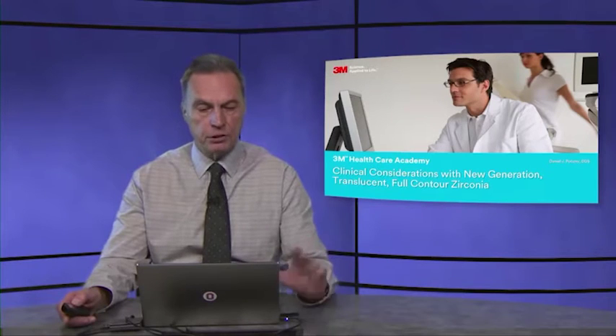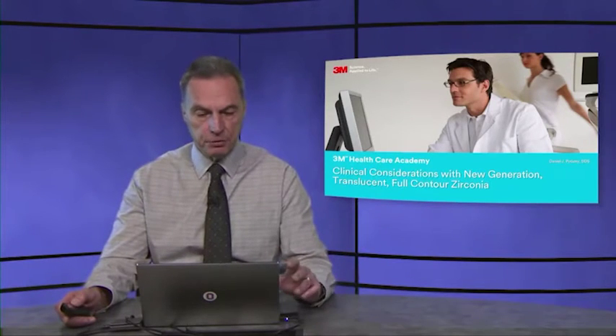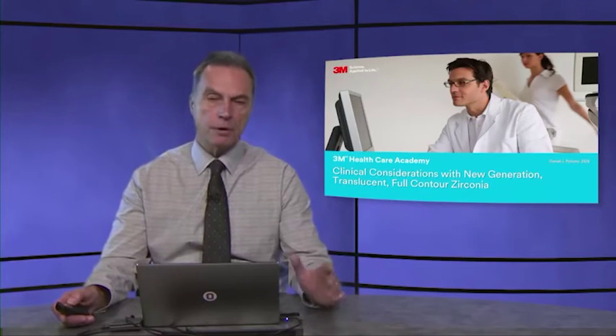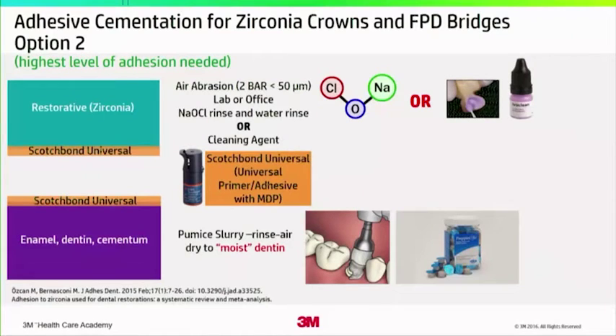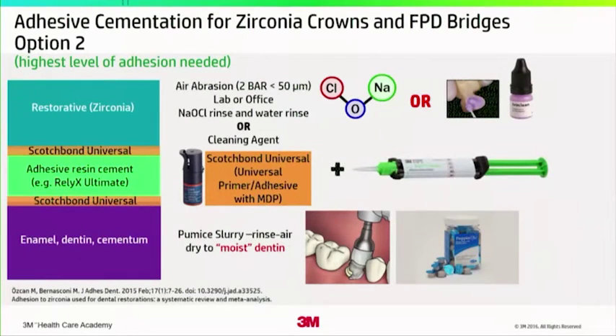So our concept is going to be the same here. We're going to air abrade, sodium hypochlorite rinse, clean it with water or our cleaning agent, clean the tooth the same way. And now we're going to use Scotchbond Universal, which is a universal adhesive, but it's actually a universal primer. So it contains MDP. We apply it to the restoration surface, doctor applies it to the tooth, and now by using a compatible adhesive resin cement, we're going to get the highest bond values attainable with any type of adhesive systems that are available today.